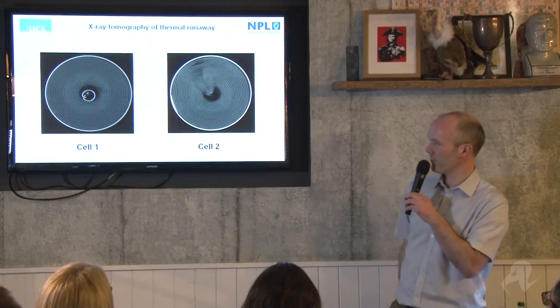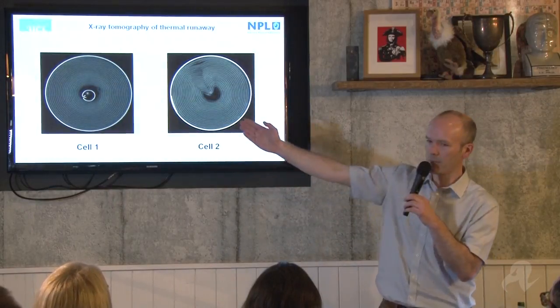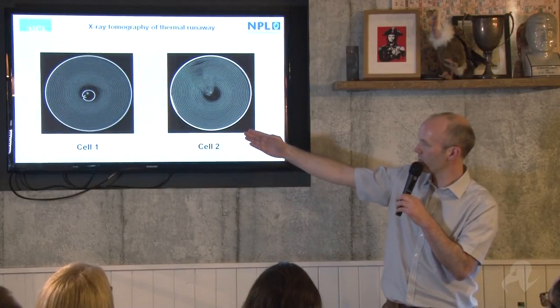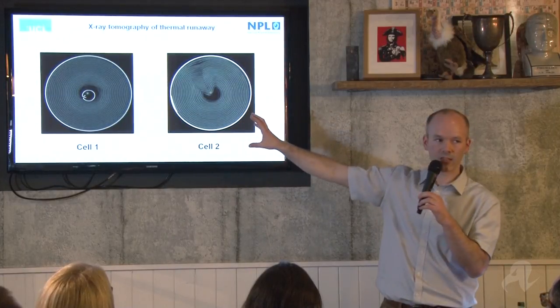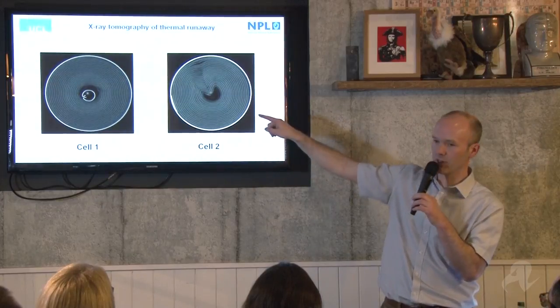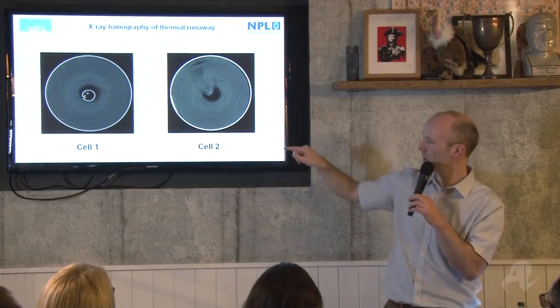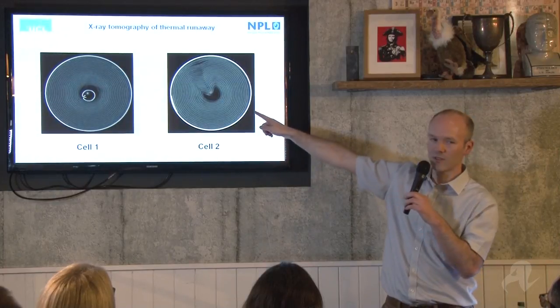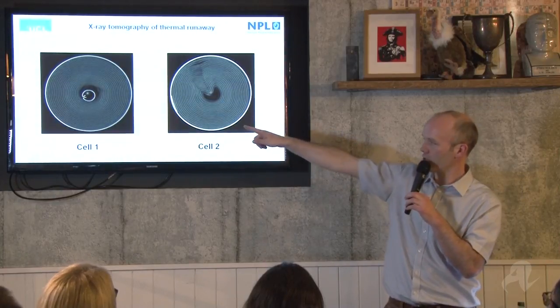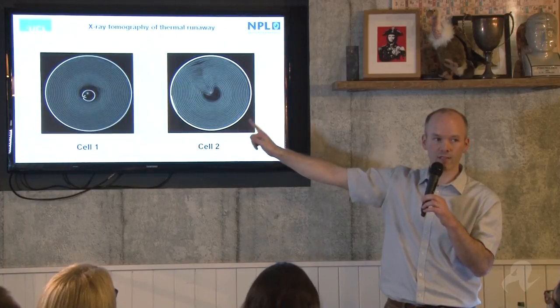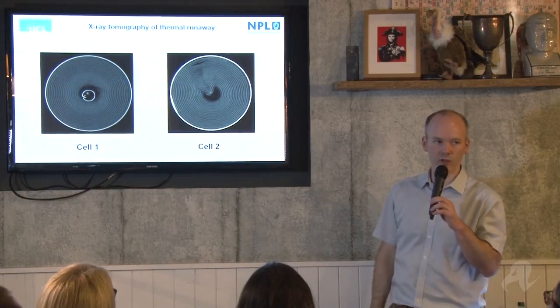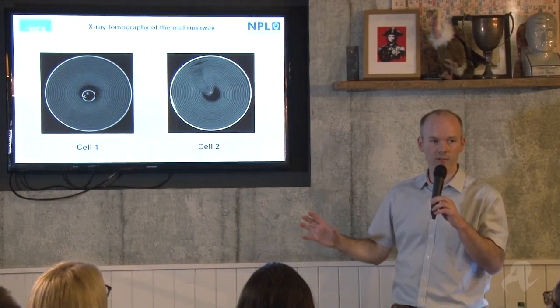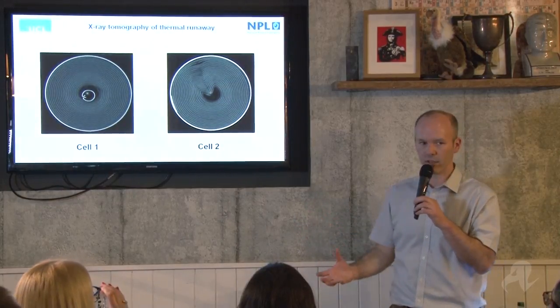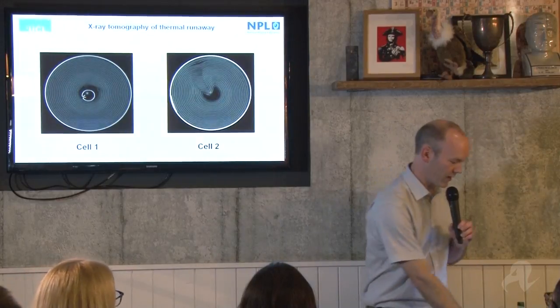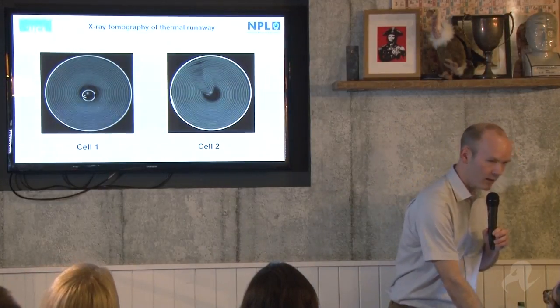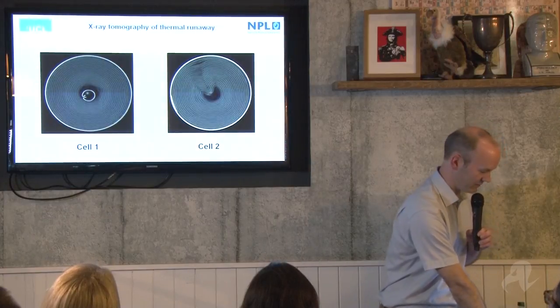What did it look like afterwards? There's cell one. The mandrel's been bashed about a bit. There's a bit of damage, but most of the cell actually stayed intact. The damage that we saw in the video is further down. This one, on the other hand, got completely destroyed. So again, this shows that including the mandrel is definitely a good idea from a structural point of view. It does have some downsides from the point of view of gas evolution, but again, that's for the designers to worry about.